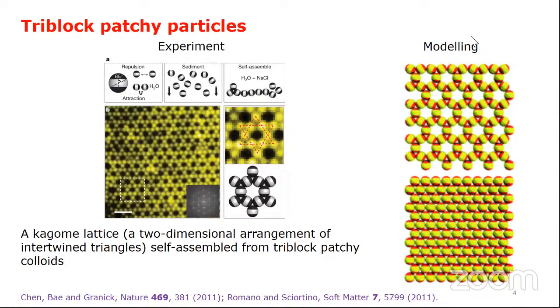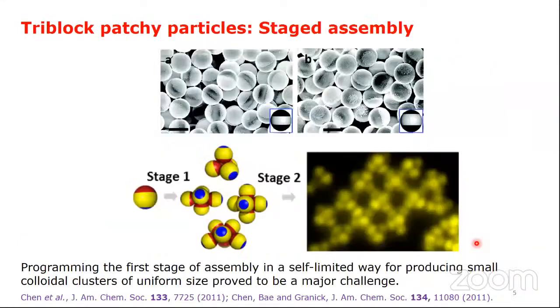So, for example, Romano and Sciortino captured the self-assembly of the Kagome lattice from tri-block patchy particles at low temperatures and pressures, and predicted the formation of the closed-packed hexagonal lattice at higher pressures. The state-of-the-art experimental fabrication has control over the patch width. In a subsequent experimental study, the Granick group induced staged assembly in 3D by changing the ionic strength of the medium in steps. However, the first stage produced a distribution of clusters leading to the self-assembly of amorphous structures in the second stage.